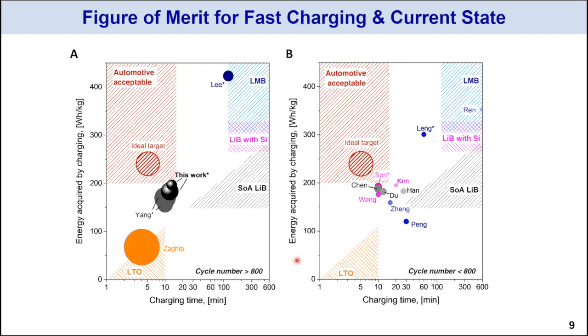So here I show you a pair of figures. And on the left, you basically have the data points or the technologies with cycle number exceeding 800, the so-called automotive target. And then on the right, you have more or less emerging chemistry and systems that have a cycle number still short of the automotive target. In each of the figures, I also have a few shaded areas, and the upper left corner here is what we define as the automotive acceptable box for fast charging, basically defined by less than 15 minute charge time and more than 200 watt hour per kg acquired energy. And within this box, there is an ideal target located here with a sizable bubble, meaning it has to be long lasting, even after fast charging.